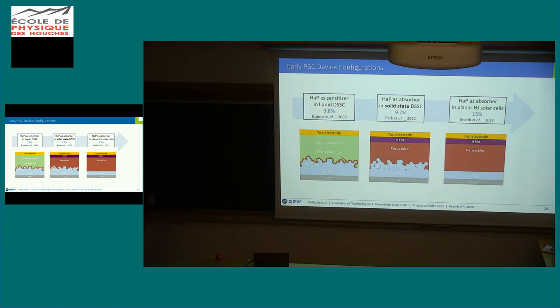The next big step was really done by Namgyu Park in 2012. It's actually a paper that was, so if you hear him talk about how it got rejected and so on, it's interesting, given on how much impact it had. So here now they used a thick perovskite film. So the liquid electrolyte was actually removed, and you had the infiltration of the titanium oxide nanoparticles, but the perovskite itself was not just a dye, but also acted as a transport film, or at least facilitated transport of free carriers through it, then topped off by a hole transport material.